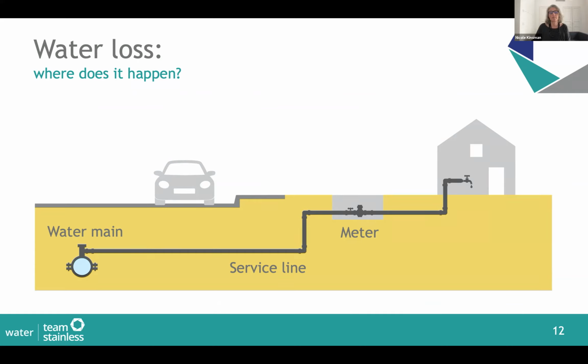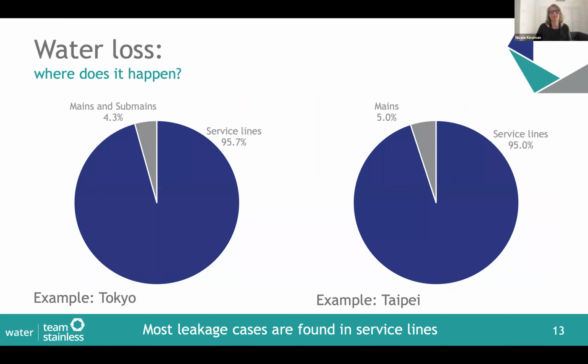And the service line between the main and the meter, and of course, also to some extent on the customer side, those service lines often have several connections, so maybe that's prone to leakage. The materials may not be as sturdy, and it's also not easy to find the leaks in the service line because maybe they're smaller leaks, so they don't appear as readily as a water main break. But we find a lot of the leaks happen in the service line, and here is some supporting data from Tokyo and Taipei. Both utilities find that more than 95% of their repair cases are in service lines.